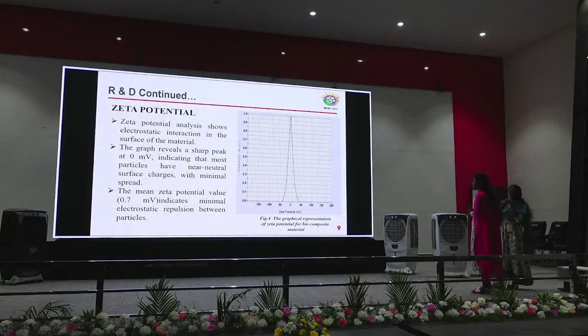Zeta potential is used to analyze the electrostatic force. In this graph, it shows a sharp peak nearly at 0 millivolt, which indicates most of the particles are neutral in charge. The mean zeta potential of 0.7 millivolt indicates that most of the material has minimal electrostatic charges.